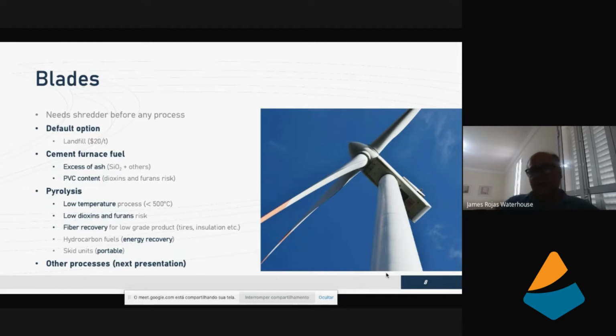So in Europe, where the problem is happening right now, just because Europe was the first part of the world to start with wind generators, they are using a lot of composite to fuel cement furnaces. But the problem is the old blades, especially, contain a high amount of glass fiber, which is basically silicon oxide and some other oxides. So the ashes that come from these processes are dominant. That's like 80% ashes and 20% hydrocarbons that could be burned and generate energy. So this turns quite expensive.